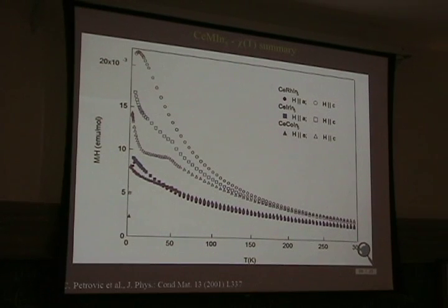Okay, so let's look at the high temperature magnetic susceptibility of the compounds. So it's a very, very simple analysis I'm going to try to do. You see that the three compounds have an easy axis, a more susceptible axis along the C axis, along the tetragonal axis. And they have very similar AB plane magnetic susceptibility. You see there is a systematic trend here that starts to develop some plateau when you go from rhodium to iridium to cobalt. So what is the origin of that? That's a complicated question actually. What is the origin of this?